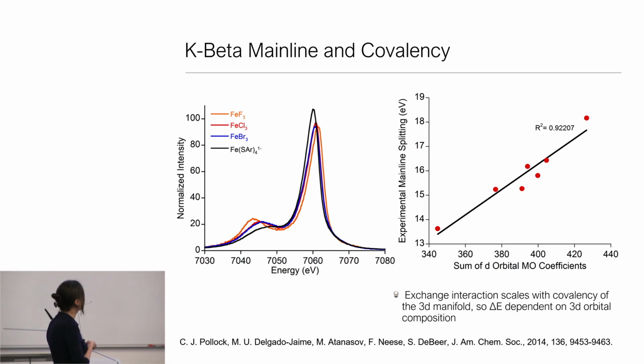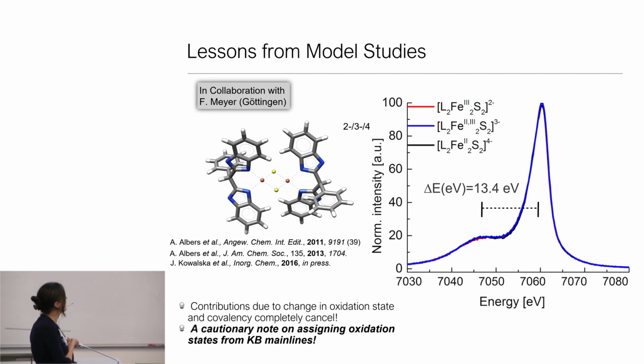But again, I always want to be honest and present the caveats, because what we do find is that covalency and oxidation state can actually cancel. There are interesting examples where the D count changes at the same time as covalency, and they 100% cancel. And yet, these are complexes that really do vary in oxidation state. They have different Mossbauer, they have different X-ray absorption edges, and it goes back to this: we need multiple methods in order to make these assignments.